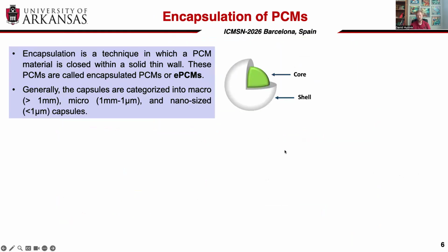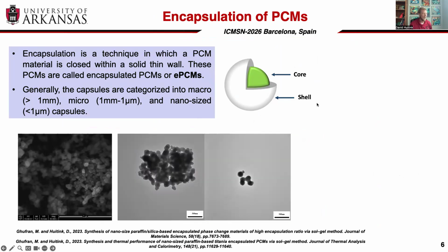And that's where we have really been focusing on this idea of encapsulated PCMs. Our ePCMs are essentially a thermally active core consisting of the phase change material surrounded by a non-thermally active shell that contains it and acts as a delivery vehicle for this latent heat storage mechanism. Here's some TEM images of what this looks like.